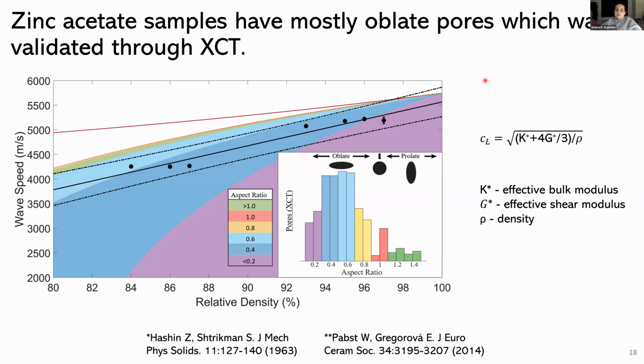So in order to confirm that the variations that we were seeing in the wave speed were actually associated with that change in the shape of the pores, what we did is we actually conducted X-ray CT in all of the samples that were composing this set. And what you see in the inset diagram over here is a histogram of the pore shapes from that X-ray CT analysis. And the nice thing about this is that this analysis essentially confirmed that a lot of the pores were actually oblate, and the response that we were getting from our ultrasonic data was actually supported by that change in the pores.